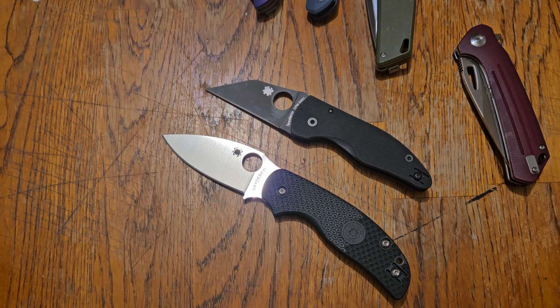Now, we can go into edge stability. That's got to be factored in, but I'm just speaking in general because I see it so much that something needs to be said about it. If you go look at Alex Outdoors 55, he did a video where he took 3 knives he made, one with about as bad a heat treat as you could possibly do, one with a perfect heat treat, one with a decent heat treat. They're all at the same Rockwell, and edge retention wise, there was absolutely no difference between the 3.